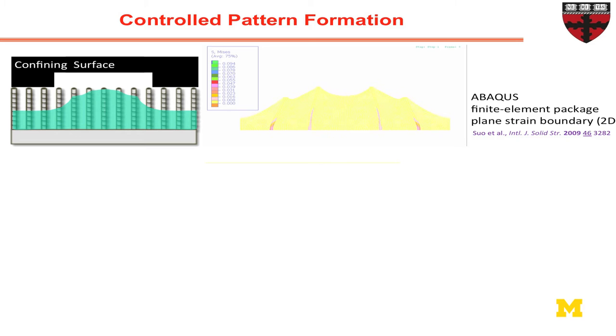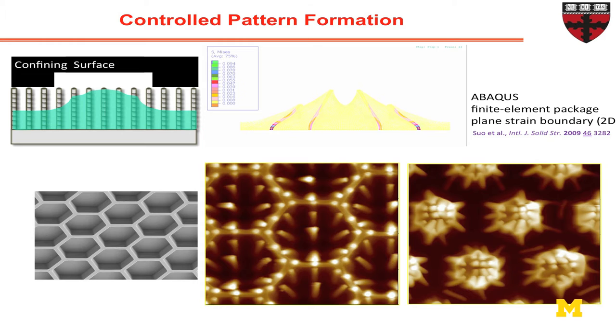You can look at that and make it more interesting by applying a structure. You can pattern your muscle. And of course you can do modeling, but it's even intuitively clear that where you have a thicker muscle, you have a higher force to move your structures around. And in this way, you can build a patterned surface that, in response to the stimulus, instead of random bending and tilting, would have very specific domains and very specific structures, in this case using a confined surface that has a honeycomb structure.